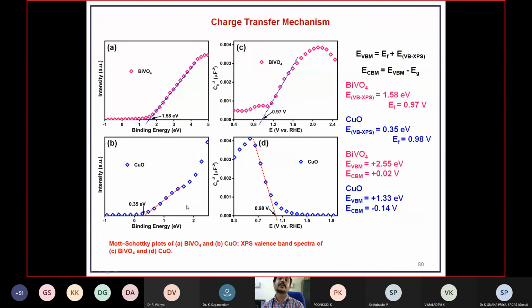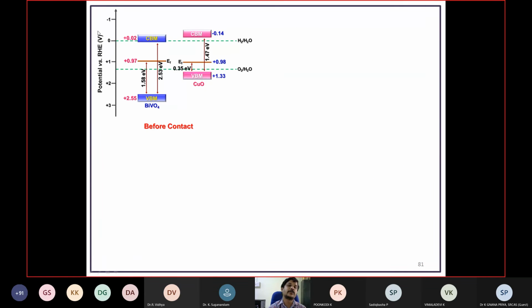Then the charge transfer mechanism is also proposed based on the valence band spectrum from the XPS spectra. We have calculated the binding energy value and band position. Then the Mott-Schottky analysis, we have calculated the various parameters from this equation. Then we substituted the values, derived the band positions, and finally we ended up with these band positions.